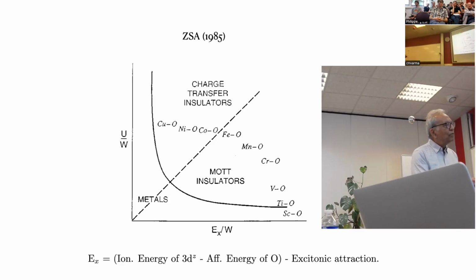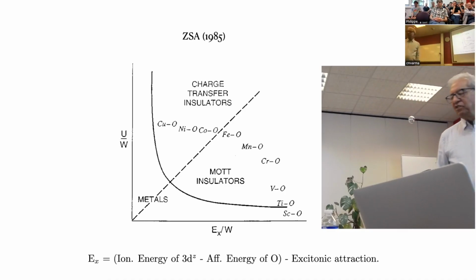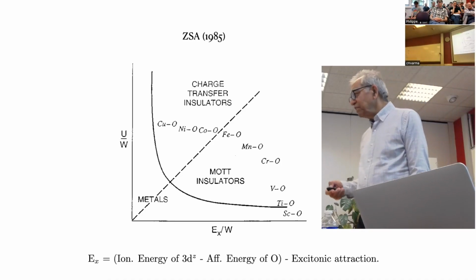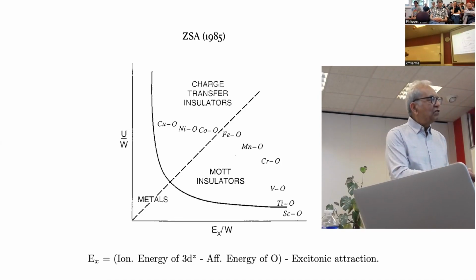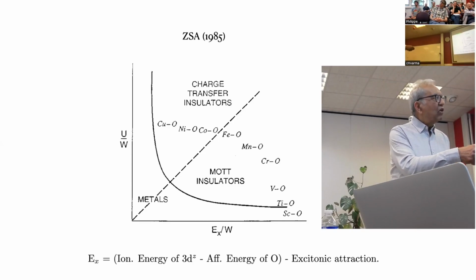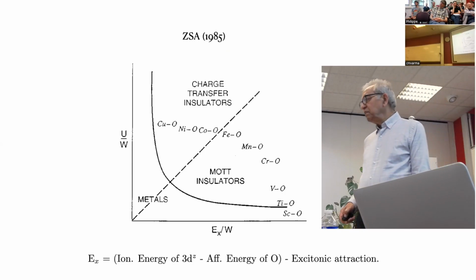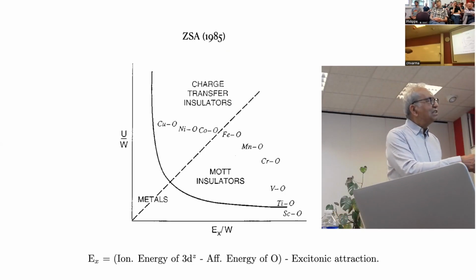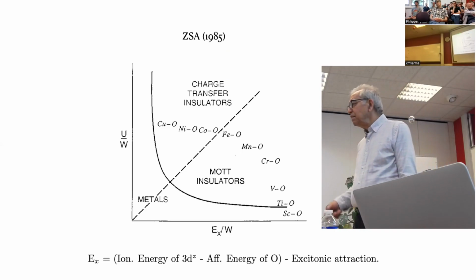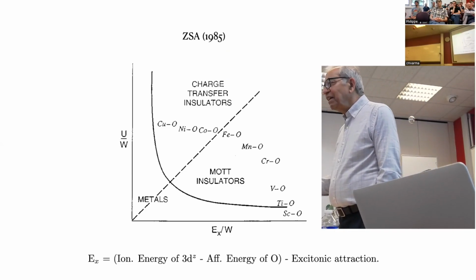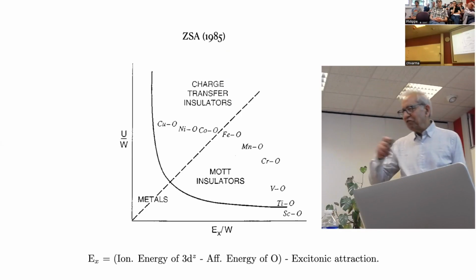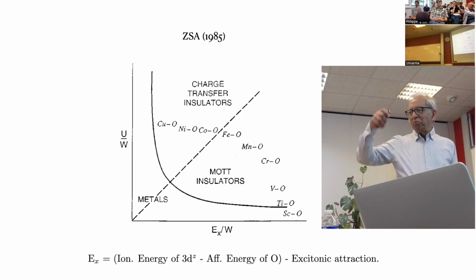If you say U is the repulsion and W is the bandwidth, and another parameter, which is the change of energy from copper to oxygen, which I just talked about, divided by the bandwidth, then you can draw a boundary, and these they call charge transfer insulators, and these they call Mott insulators, and these things here would be metals. Nickel sulfide is an itinerant metal. For example, sulfur, the levels go up compared to oxygen.